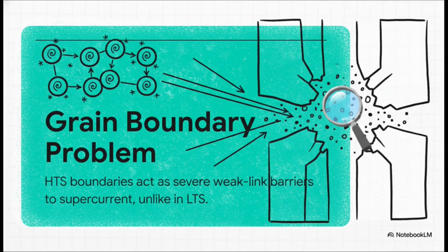But in HTS cuprates, the exact opposite happens. These grain boundaries act as severe weak link barriers. So instead of helping the supercurrent flow, they completely block it, shifting the material into an insulating or semiconducting state where charge carriers are basically forced to tunnel between grains.